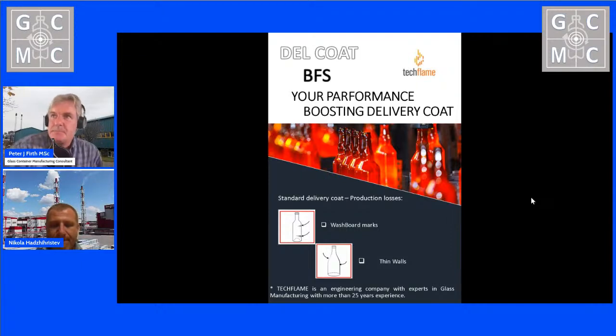There's one thing that's been mentioned to me directly recently when I put this notice out about the event. They're interested in a better coating because they're getting little black specks from the coatings they're using wearing, and getting on the bottles. And they were talking about rejecting a few percent. Personally, I've never experienced that, but I suppose it depends what coating you're using. So theirs was like a cosmetic problem with the coating wearing. Could have been coating wearing or could have been carbon, I don't know. But they were getting black specks in the containers. So that's another problem that some people have when the coating wears.